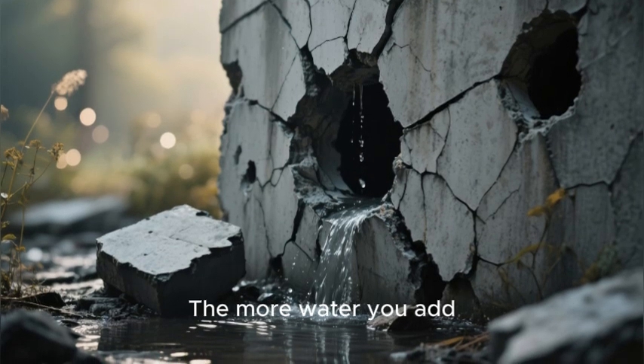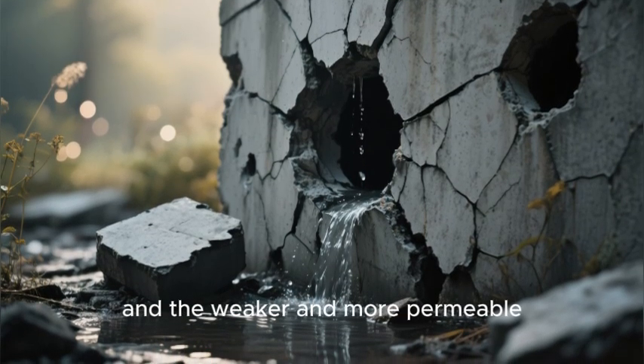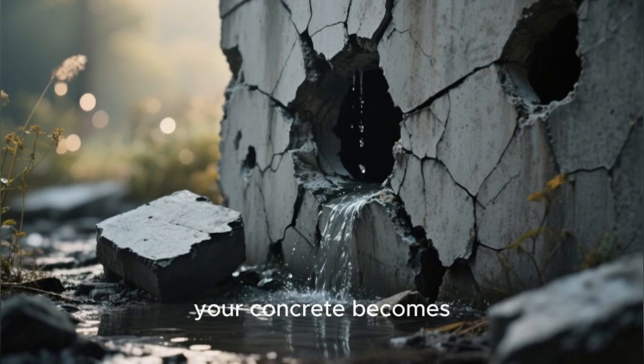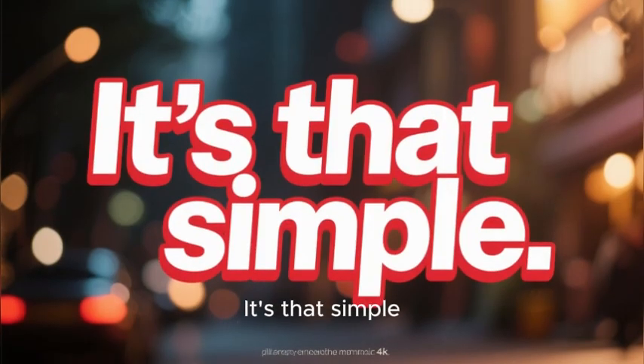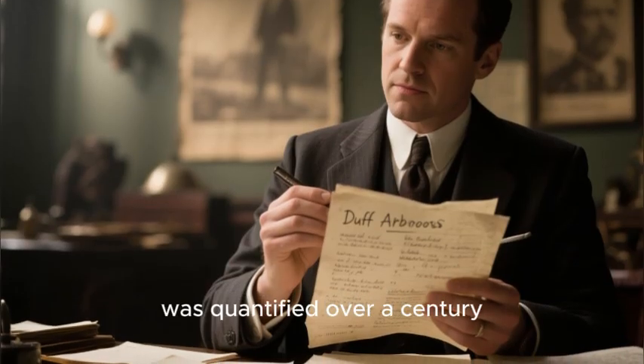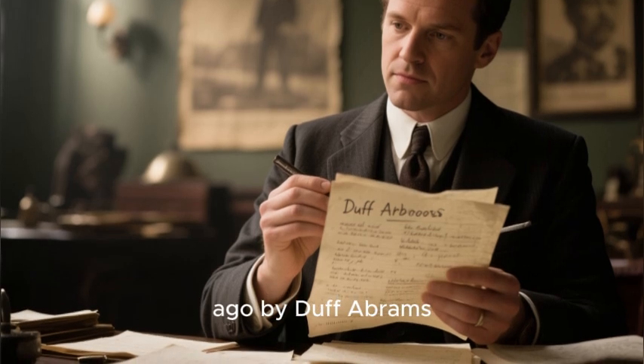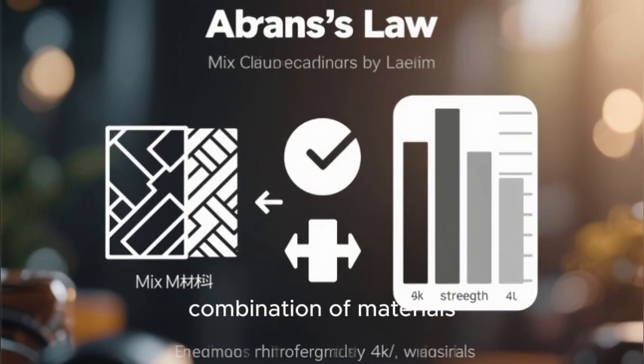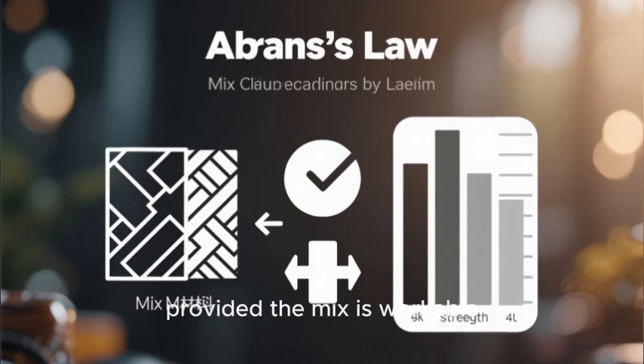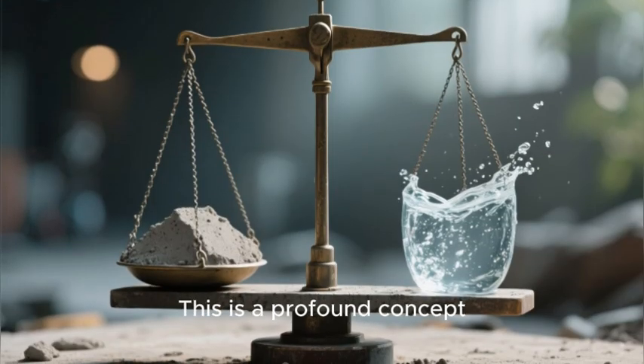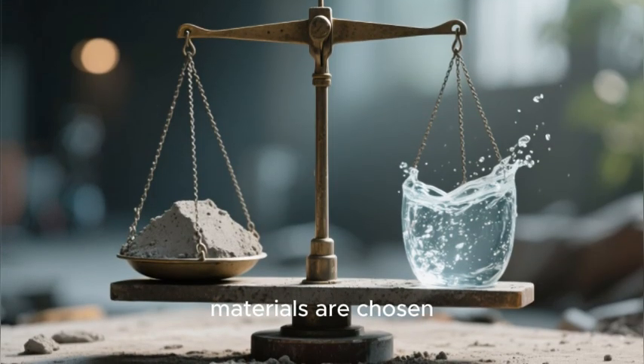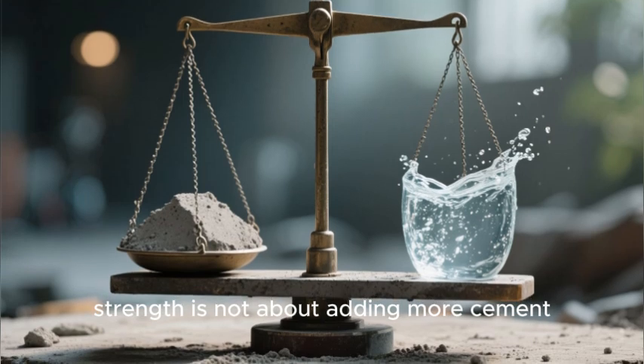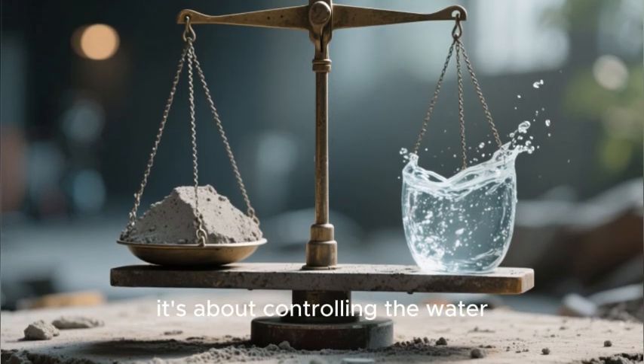The more water you add, the more pores you create, and the weaker and more permeable your concrete becomes. It's that simple. This relationship was quantified over a century ago by Duff Abrams, who established Abrams' law. It states that for a given combination of materials, the strength of concrete is determined only by the water-cement ratio, provided the mix is workable. This is a profound concept. It means that once your materials are chosen, strength is not about adding more cement, it's about controlling the water.